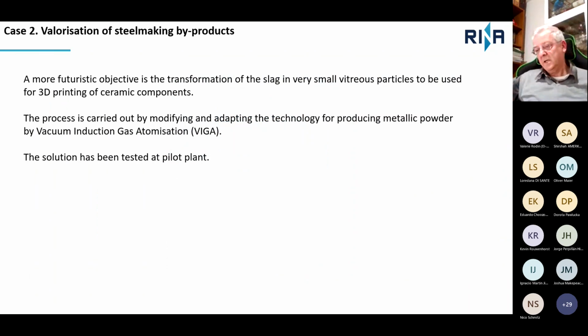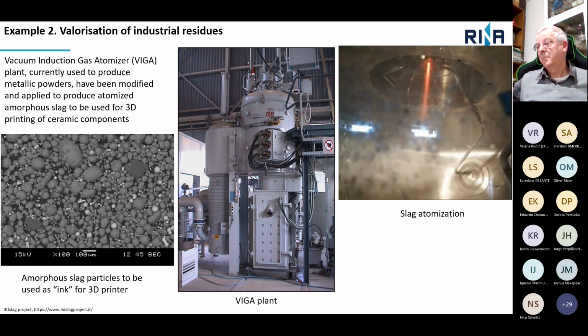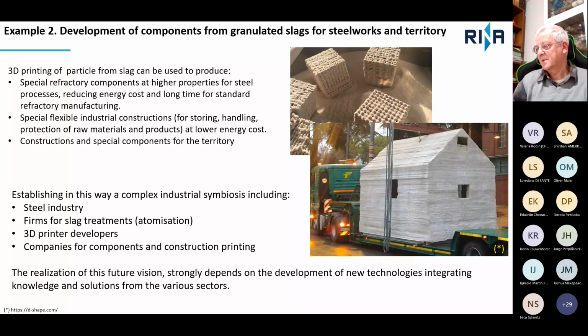Finally, as a last thing, it can be possible to use atomized slag, which means to produce very small particles to be used in possible 3D printers for printing ceramic components. In this example, we have performed atomization of a slag, producing very fine amorphous slag particles, around 50-100 micrometers, with a typical vacuum induction gas atomizer for producing metallic powders. In this case, we have adapted the technology to produce slag powders, and there are experiments in progress to produce special components for the steelwork itself, or also for other contexts.